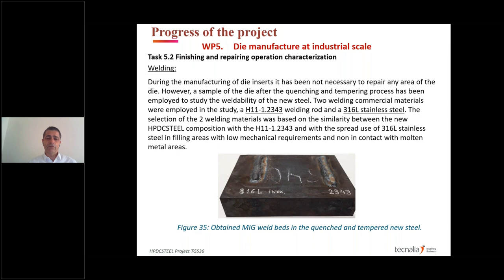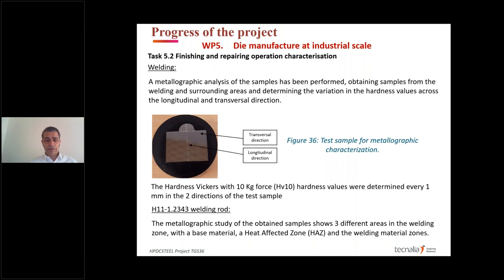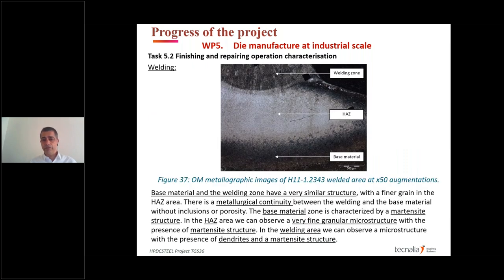We made some welding tests with an H11 welding rod and also a 316 stainless steel, in this case for filling the dies. We also measured the hardness on the HPDC steel. What we observe is that when we weld with the H11 rod, we have a good transition between the base material, the heat affected zone, and the welding zone. There are differences between the microstructures, but the microstructures are quite good in all three areas.